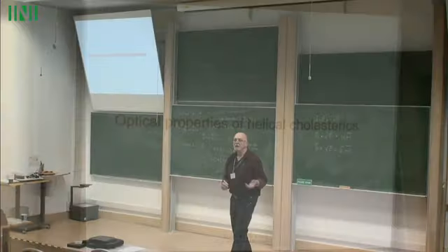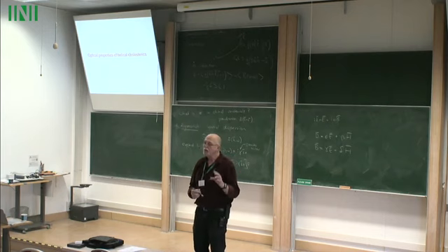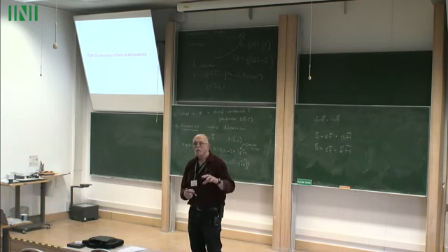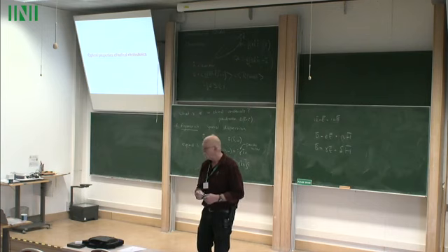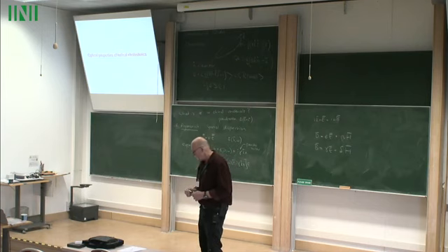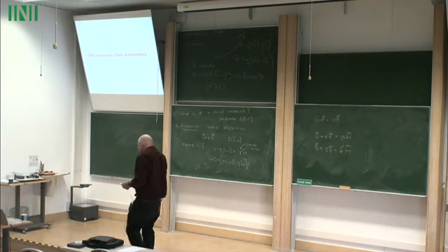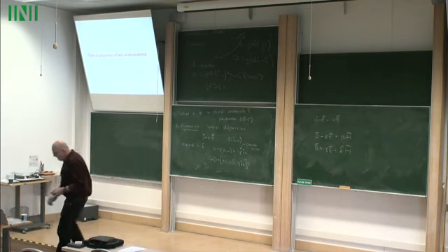Now, to make these materials, typically people take a chiral dopant, a pretty highly chiral molecule, and dissolve it in an ordinary nematic, and then you get this chiral structure. And so one noticeable feature is that these systems are periodic, and periodic systems have interesting properties, and that's what will be manifest in a minute.